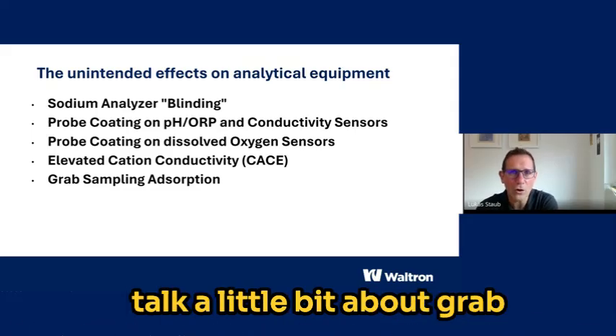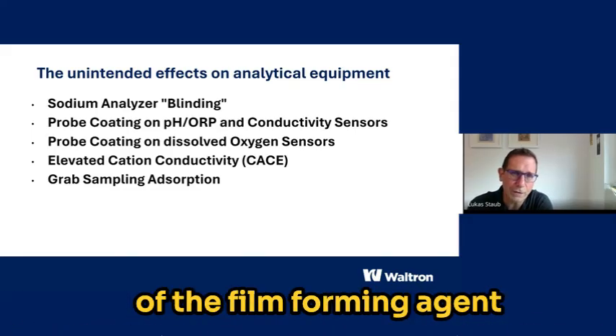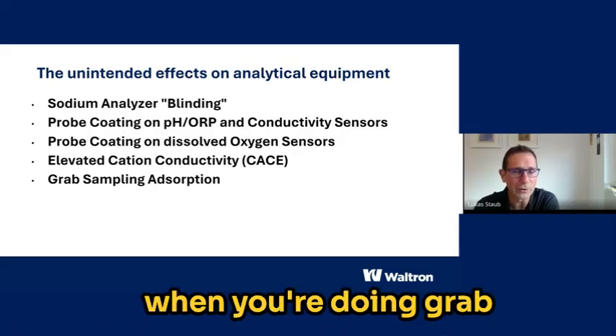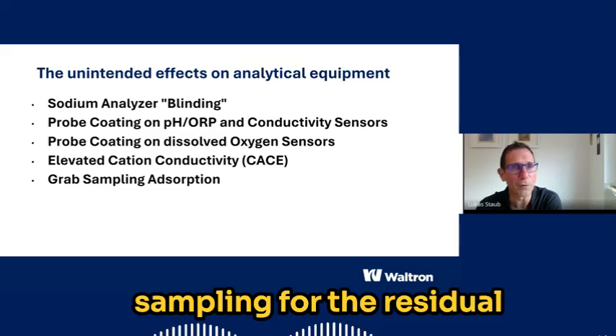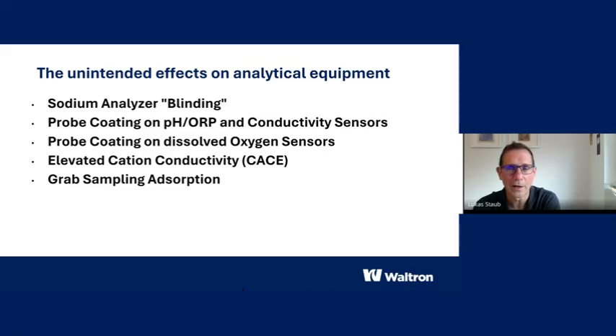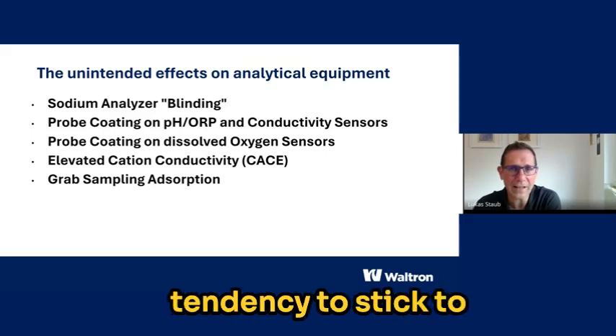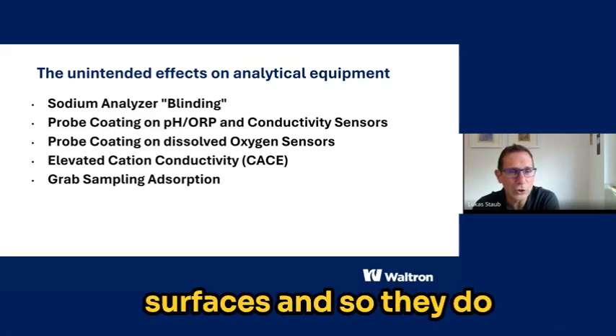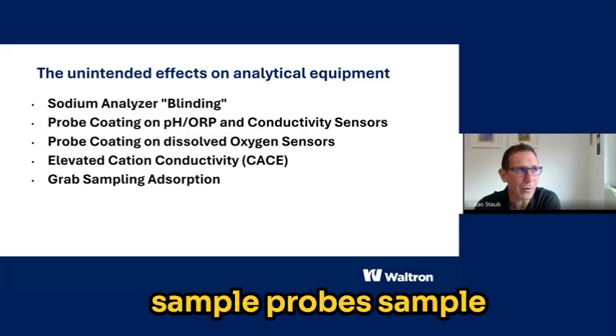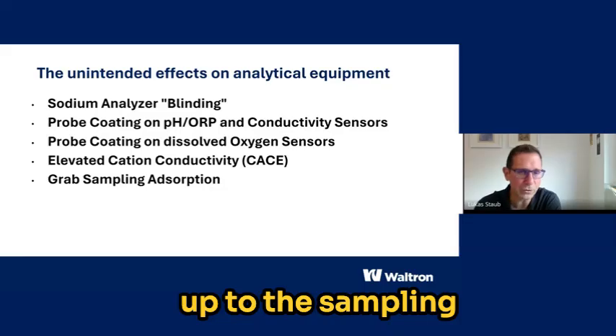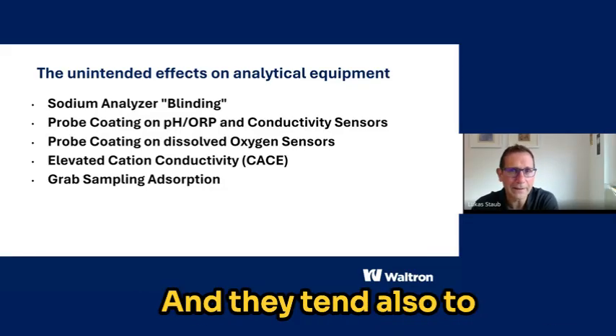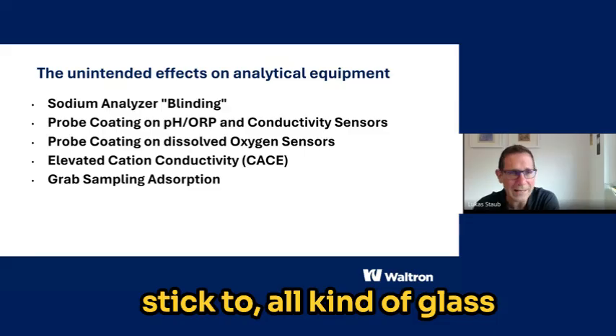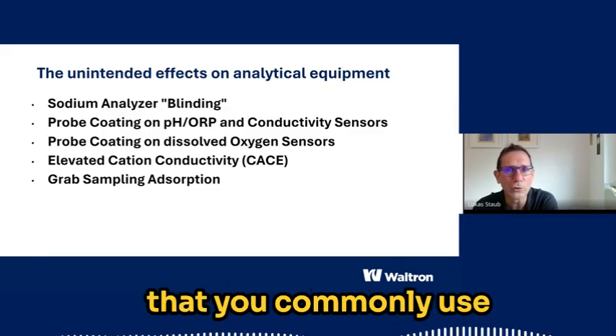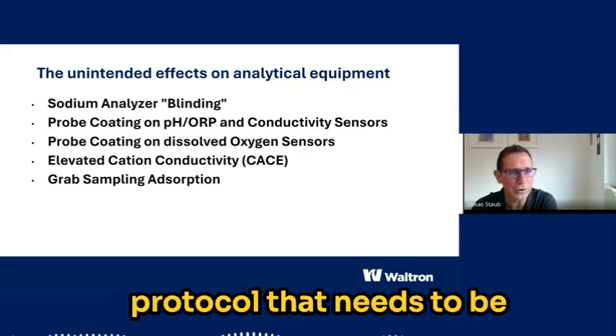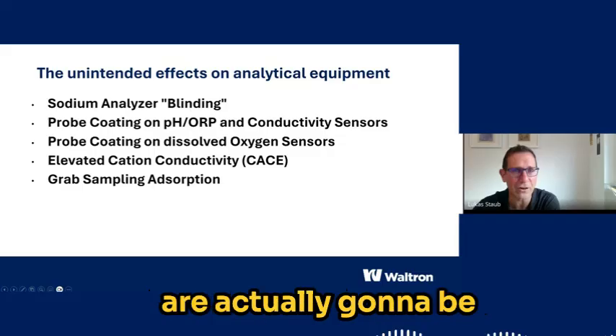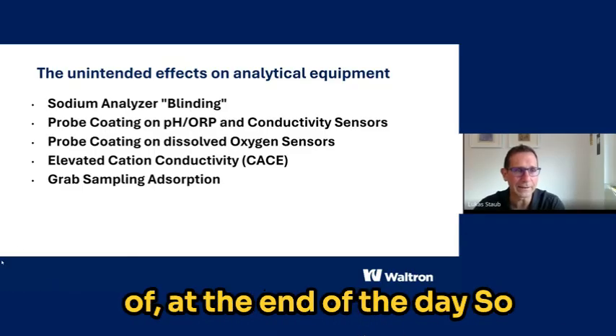Last but not least, I want to talk a little bit about grab sampling and absorption of the film-forming agent when you're doing grab sampling, and especially when you're doing grab sampling for the residual FFA that you're using. As always, the FFAs, FFPs, they have a tendency to stick to surfaces, and so they do stick to surfaces of sample probes, sample tubes that are leading up to the sampling system, the SWAS panel, and they tend also to stick to all kinds of glass bottles and containers that you commonly use for your grab sampling. So there is a certain protocol that needs to be established to make sure that your grab samples are actually going to be representative at the end of the day.